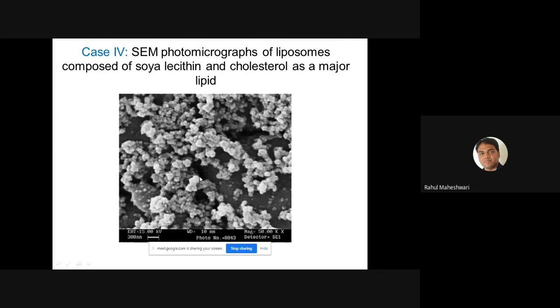And what is it confirming? It is confirming the occurrence of the particles; we are able to see hundreds of particles in this image, number one. And what does it support? It supports the formation of liposomes, and the proposed configuration for this particular method, right? And this was prepared with pressure near about 180 bar and temperature at 50 degrees centigrade. Why can we not increase the temperature? Because we are playing with the lipids in the case of liposomes, so every time it must be somewhat above the phase transition temperature of the particular lipids that we have used in the formulation.